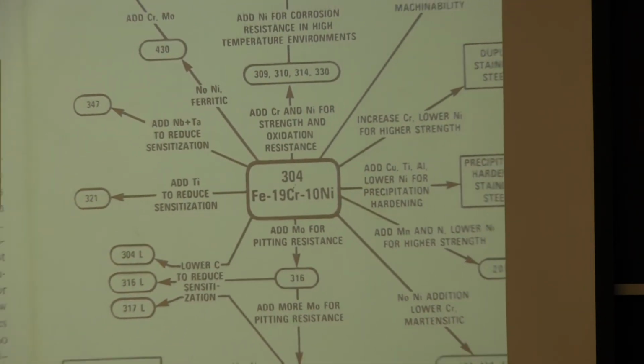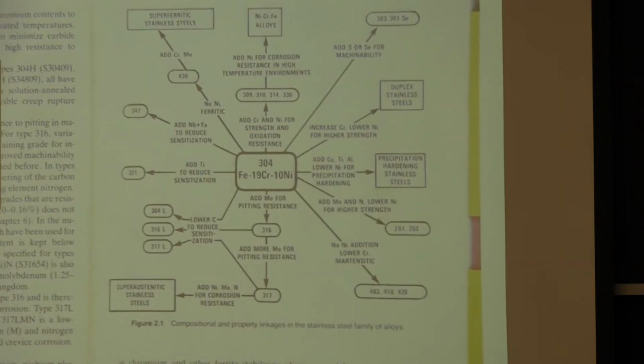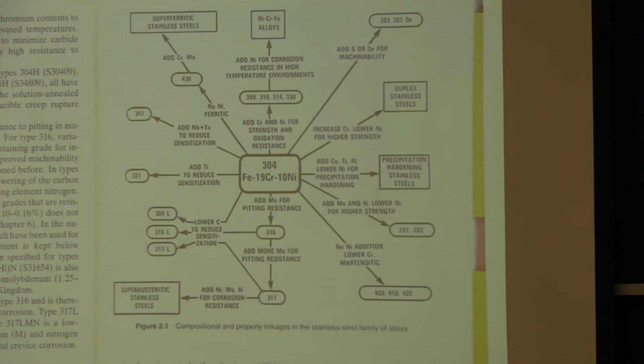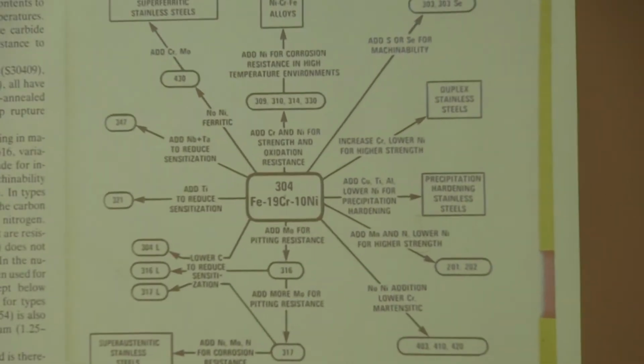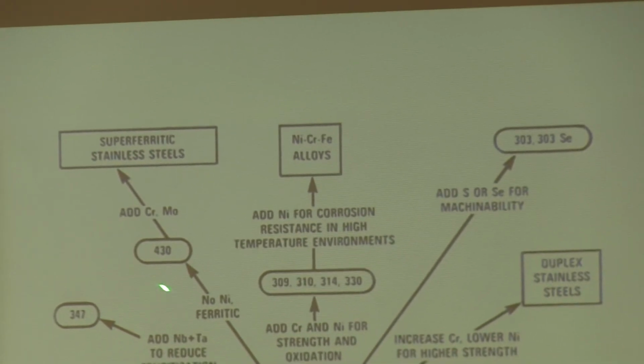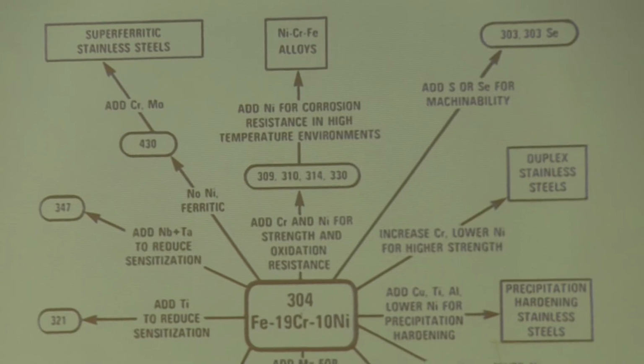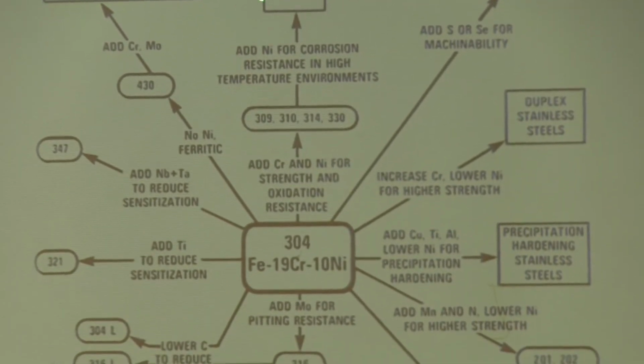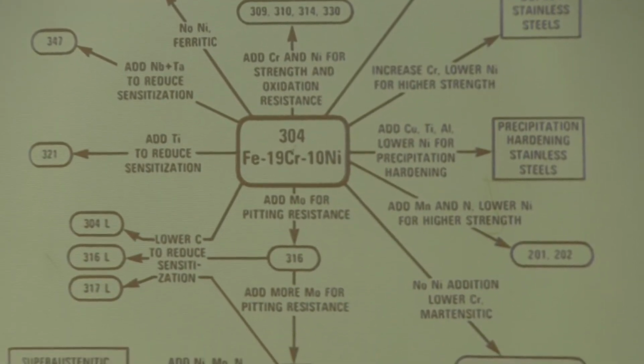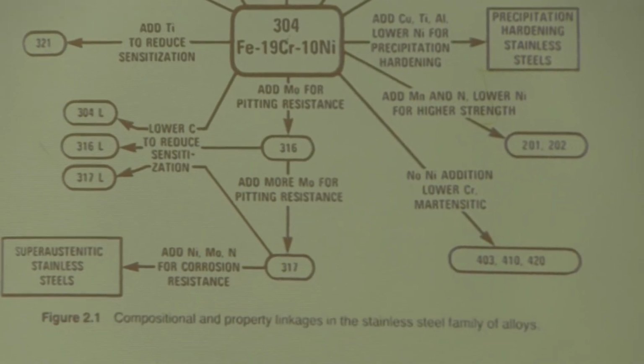So this is a diagram that Professor Eager actually gave me the other day, and it's a diagram that demonstrates that 304, like I said, is kind of that centerpiece alloy of the austenitic stainless steels, and then depending on what you're adding or subtracting, if you're adding a little bit of molybdenum, then you come down here to the 316 alloys. If you end up adding a lot of chromium, you move all the way over to the ferritic alloys. The more nickel you add, the closer you move to the nickel alloys, which we'll talk about in a few days when I lecture again. So the real essence of this is that the 304 and then various modifications of that are at the centerpiece of the austenitic alloys.